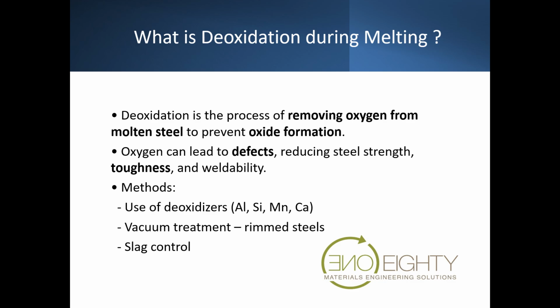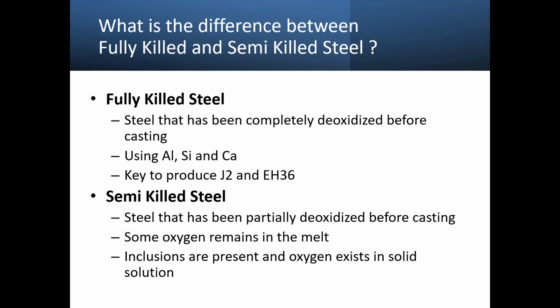So the stuff that sits on top of the steel has to be scraped off before it's poured into the continuous caster. So a fully killed steel means that the steel has been completely deoxidized before casting, using things like aluminum, silicon, and calcium. And this is key to producing J2 and EH36.